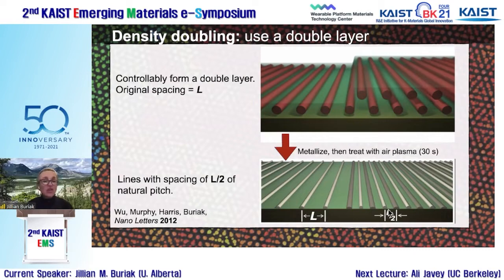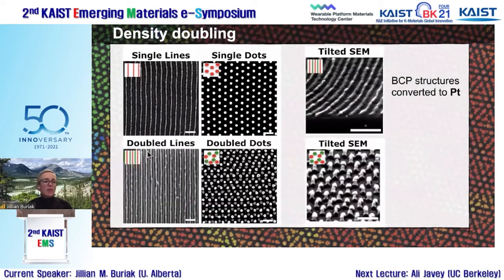And you haven't even changed the block copolymer. So you can choose a block copolymer that gives you nice regular patterns because it's sufficiently large, has good segregation force, but then we decrease it by a factor of 2. And so this actually works. And so we're looking at the single dots and the single lines, and then we can make the doubled lines from the top to the bottom.